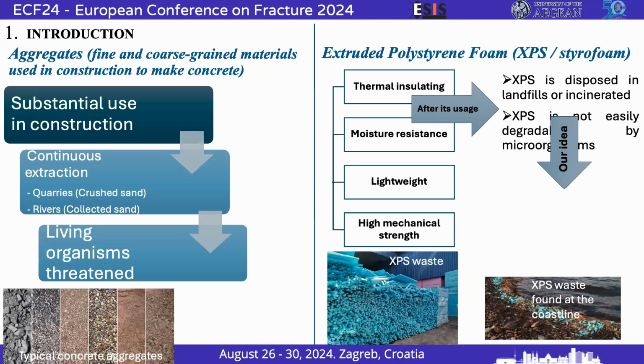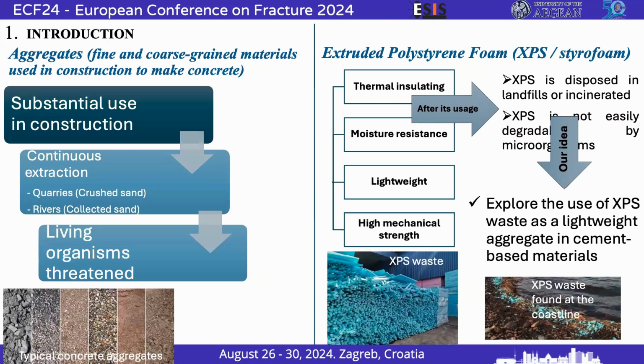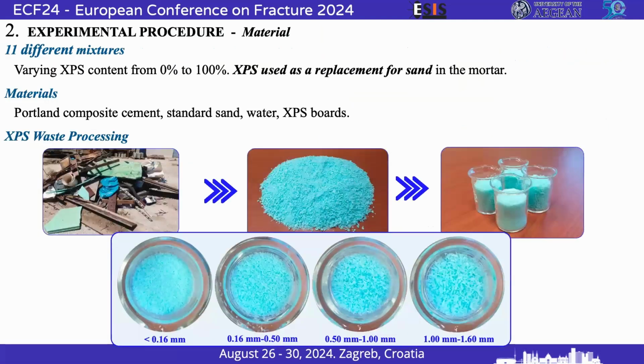So our idea is to incorporate this type of material after its usage, this waste actually, and explore its possible use in cementitious materials in order to substitute sand and develop a new type of composite. In order to do that, we prepared several mixes and studied its effect. We gathered XPS waste, processed it, ground it, and characterized it according to its particle size. And we developed several mixes, 11 mixes with varying XPS content from 0 to 100%. We substituted sand in our material.